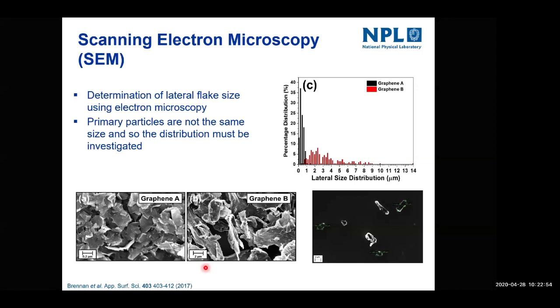Now, a big issue with this, of course, is that a lot of SEM measurements might look like these here, the graphene A and graphene B. That's great to get an understanding of what the morphology looks like. Does it look like a flake or spheres or scrunched up? What does it look like? But actually, what we need to do in our protocol is get the sample preparation correct, so that we can essentially isolate the flakes, so we can then measure the lateral size, so we can then produce this type of histogram here. So following on from the SEM, we've got an idea of lateral flake size.